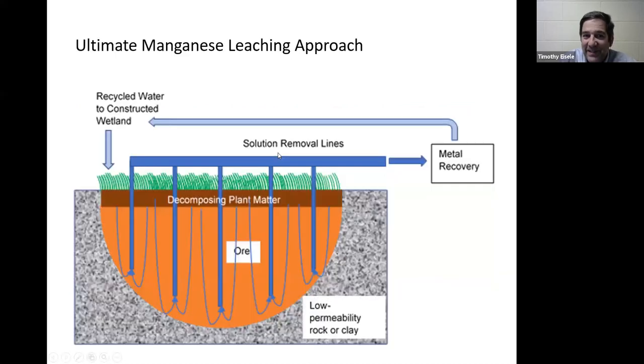So for the manganese, the concept is similar to what we have for the iron, except in this case, we don't have to make it into metal. The big market for the manganese is as the battery market, and the battery market wants manganese dioxide. So all we need to do is dissolve it, bring it to the surface, and then bubble oxygen through the solution to reoxidize it to manganese dioxide. It's now not soluble, drops out of solution. We recirculate our solution back to our wetland and dissolve more manganese.